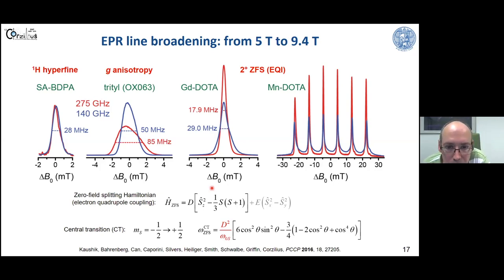Then there's another question: what are other d and f configurations of metals that would demonstrate g value close to g e? For example, chromium, I will also show this in a moment. For example, in the d3 system, in principle, every time you have a non-degenerate ground state, that means you cannot put the electron by choice practically in one or the other orbital, but you have an energy difference between the orbitals. For example, if you have a t2g system, so three degenerate orbitals in an octahedral ligand field, and you only put one electron in there, it's already degenerate because you can choose in which orbital you want to put it, and this immediately introduces the orbital momentum.